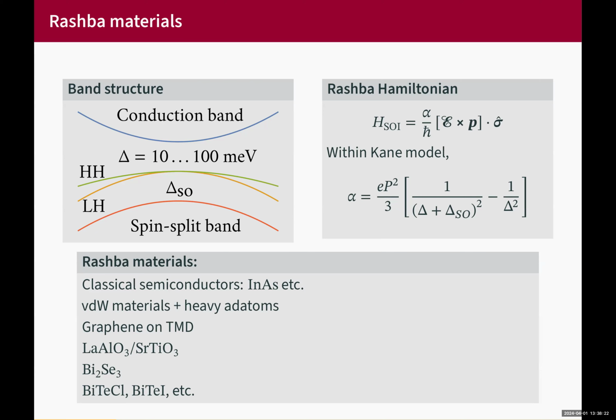But note that the valence bands are split by spin, and the reason for the splitting is exactly this very relativistic spin-orbit interaction. Normally, the splitting in the valence band is large when the material contains some heavy elements. And those heavy elements create very large nuclear fields, and the splitting is proportional to Z to the 4th. So for heavy elements, this can become large.